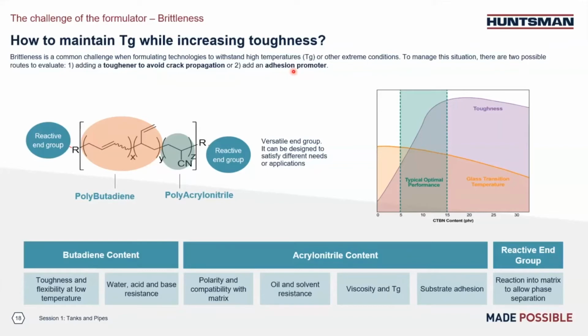And the toughener we're going to talk about is based on reactive liquid polymer. If we look at these structures, this kind of reactive liquid polymer is basically a copolymer of butadiene and acrylonitrile. The butadiene brings us very good toughness and flexibility, even at lower temperature, because it has a very low TG, like minus 40 degrees C. It also gives us good water resistance. On the other side, the acrylonitrile function will bring us chemical resistance and TG. And also because of its polarity, it will improve the overall adhesion. We also can add different reactive end groups to meet different end applications.